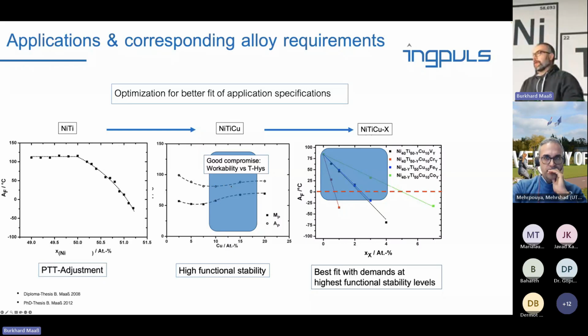So how can we now take this small hysteresis material and decrease the transformation temperatures? We add a fourth element, we call it X, and these are elements that are between nickel and titanium in the periodic system of elements. So that would be vanadium, chromium, iron, and cobalt. And you might argue that manganese is missing. You don't want to put manganese in your vacuum induction furnace because it evaporates and it messes up your whole furnace and you have to clean for hours. So that's the first thing I learned from Jan Frenzel: never put manganese in our furnace. That's why I didn't look further into this.